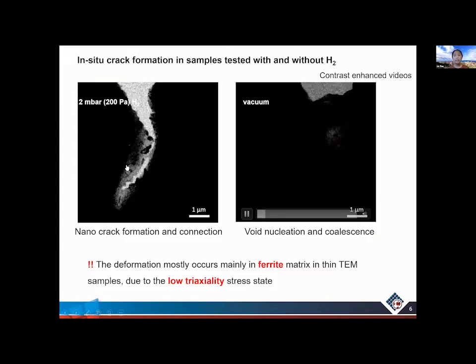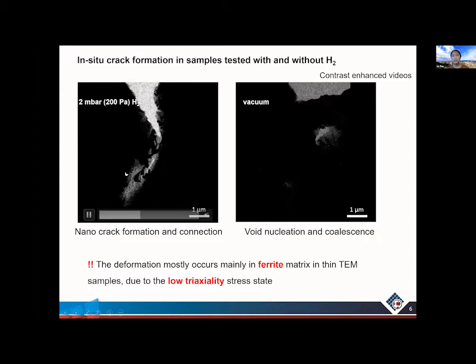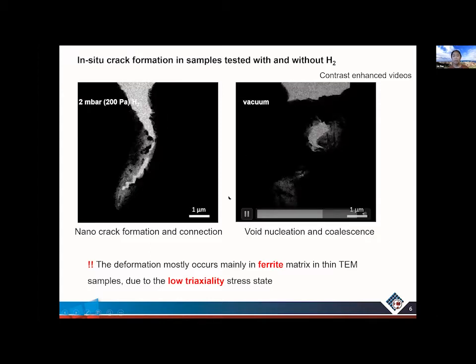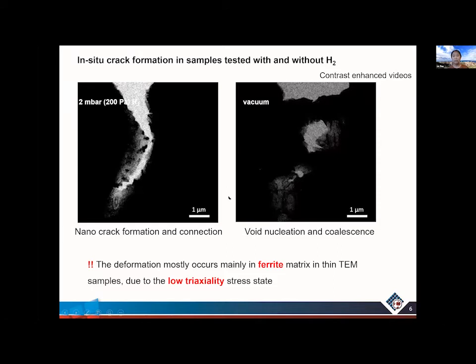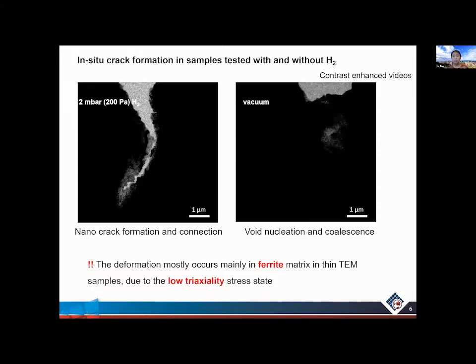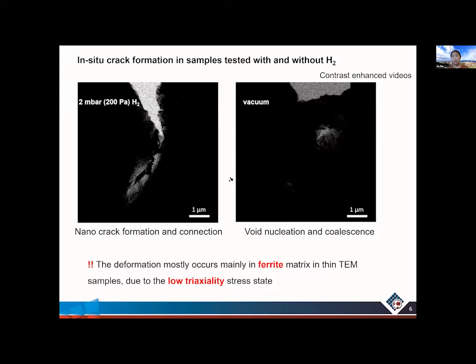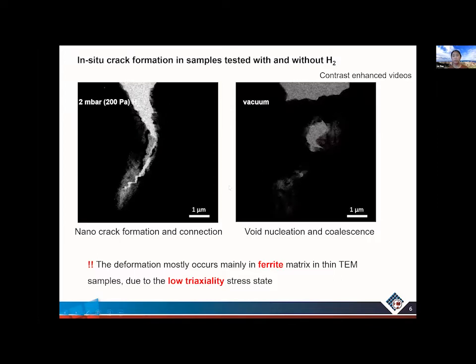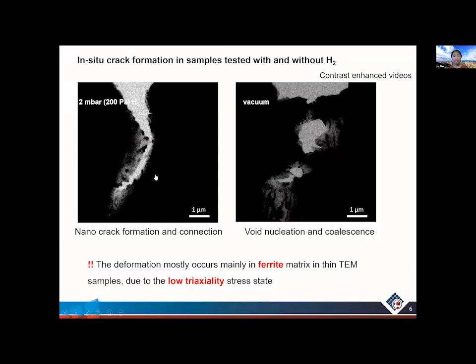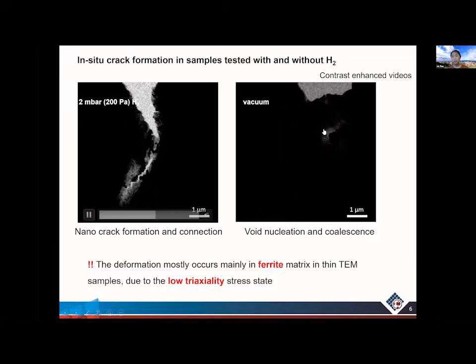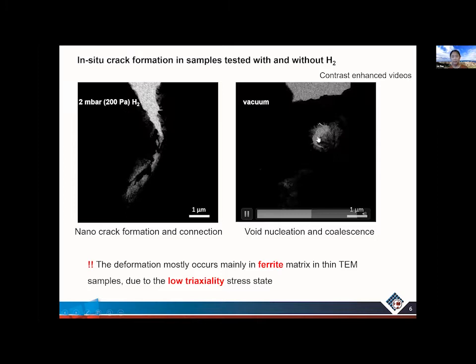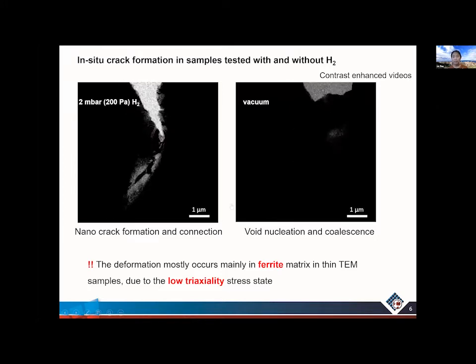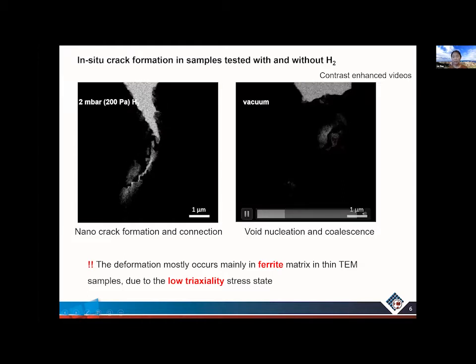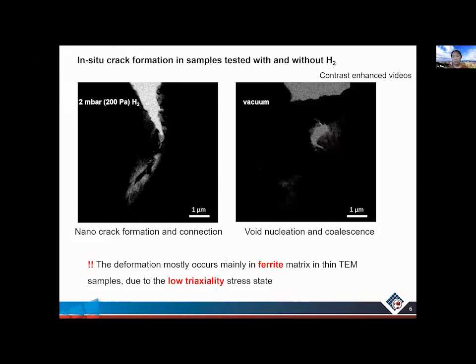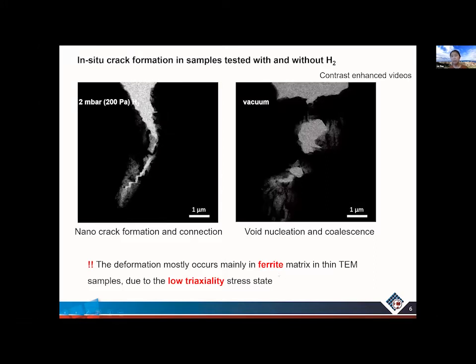Now I show you the video showing the crack formation process in 2 samples. One is tested with 2 millibar hydrogen gas and one in vacuum. In this video, it's mostly black and white, so I increased the contrast of the video to better show the formation of the crack, such as here, and also void formation in the video on the right side. I have to mention that even though you cannot see the microstructure here, we checked all the deformation. Most of the deformation occurs mainly in the ferrite matrix.